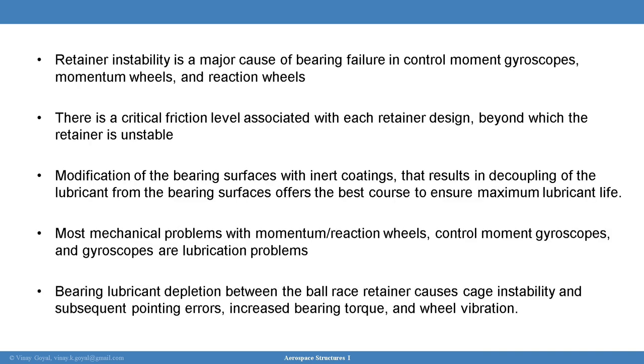You also want to pay attention to the retainer instability, which is a major cause of bearing failure in control moment gyroscopes. There is a critical friction level associated with these retainer ring designs that can make the retainer go unstable. Modification of the bearing surfaces with inner coatings that result in decoupling of the lubricant from bearing surfaces usually offer the best course to ensure maximum lubricant life. Most mechanical problems with these momentum reaction wheels, control moment gyroscopes, and gyroscopes are lubrication problems, and so you want to pay attention to those.